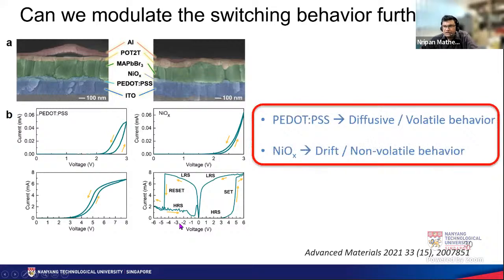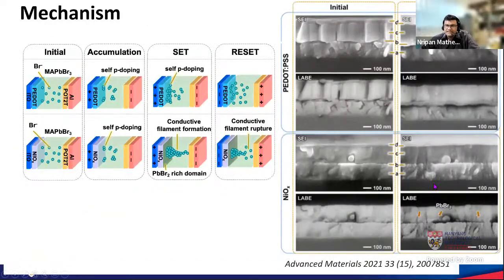abrupt switching. So the PEDOT:PSS, the same perovskite, similar thicknesses, we try to control it to be exactly similar. The PEDOT:PSS interface would lead to diffusive or volatile behavior, while the nickel oxide interface would lead to non-volatile behavior. And the reason for that turns out to be that when we are applying a voltage, on the top are the SEM images for PEDOT:PSS, below here is nickel oxide. We are able to see that under the application of the voltage, there is actually a reaction that happens between the nickel oxide and the perovskite at these interfaces. So the formation of lead bromide at the interfaces could be the reason why we have such abrupt switching characteristics for the nickel oxide, while the PEDOT:PSS was milder.